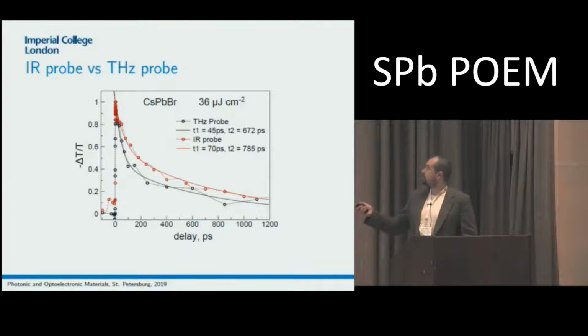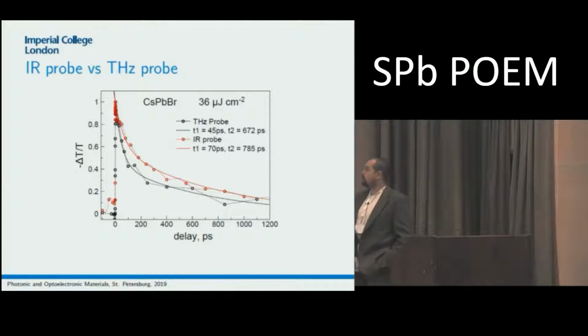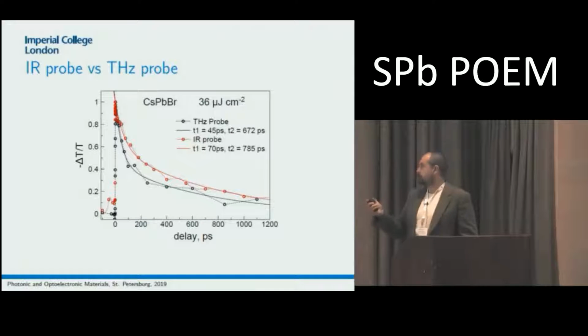These are the curves, and we can see that terahertz probes indeed happens quite faster at the same pump fluence, which can be associated with a change of carrier mobility within the cooling process, like hotter carriers that would have higher carrier mobilities if compared to colder carriers.